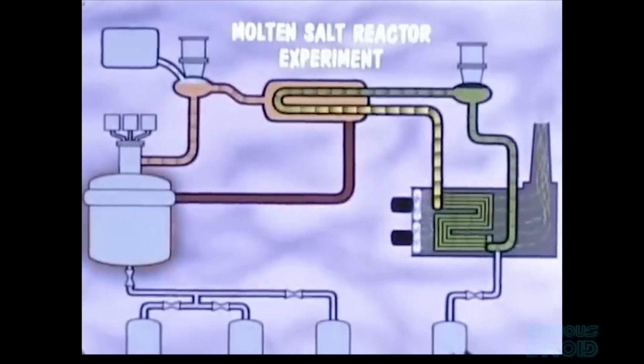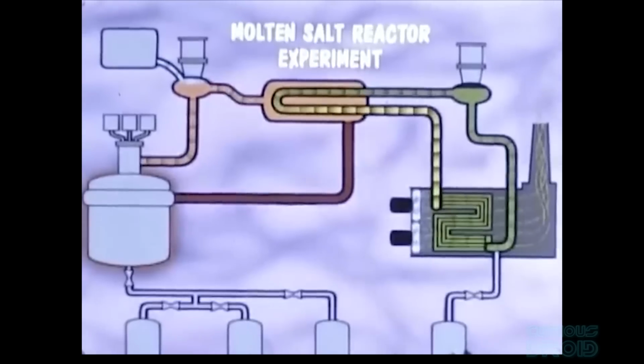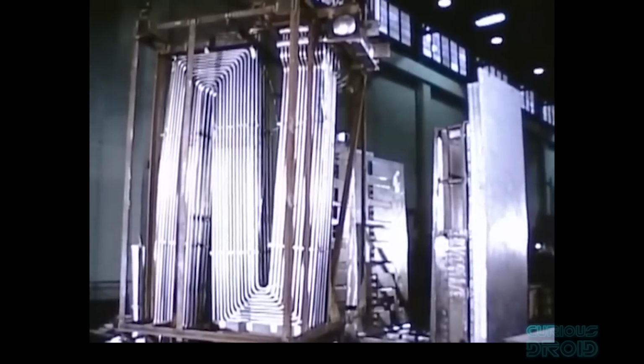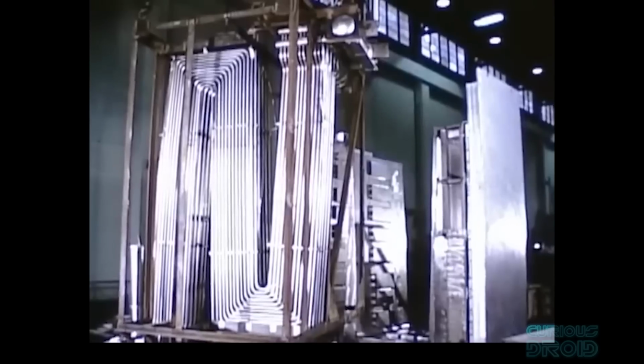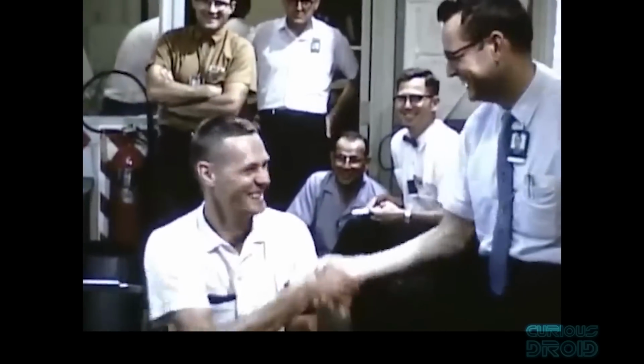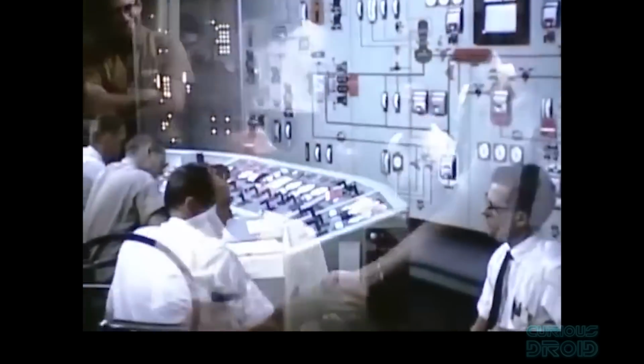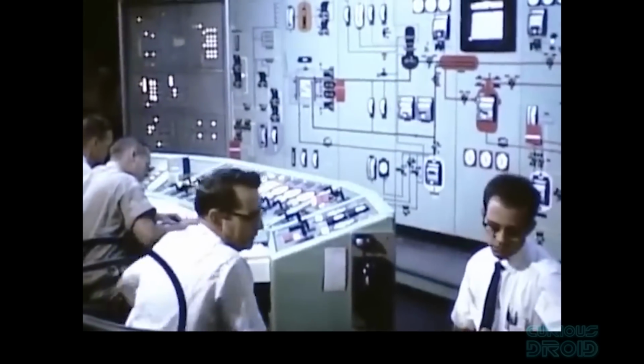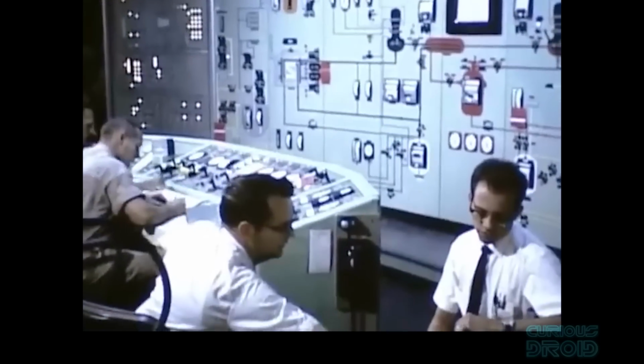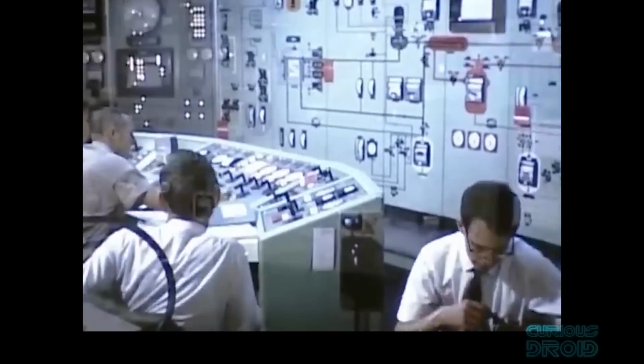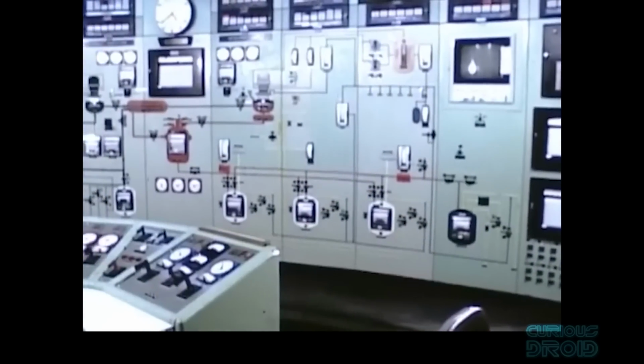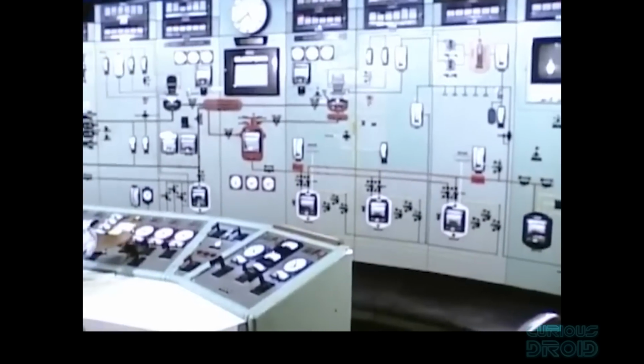As the salt-fuel mix flowed through the reactor, it would be heated up to 650 degrees C by the reaction. This then flowed through air-cooled radiators. There was no electrical generation capabilities, and it did this at full power for the equivalent of 1.5 years. Although it was operational for 4 years, there were lots of times when it was not functional due to faults and external issues. This was, after all, the first experimental molten salt reactor, and the material sciences were still in their infancy.